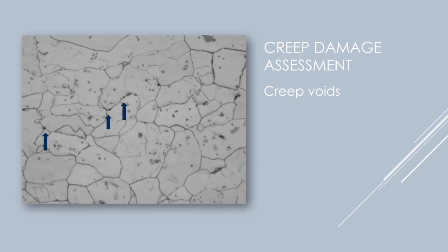So you can see all those little balls at the grain boundaries. Each one of them is a void. So they're not a particle, they're actually a little void. I've got three pointed out, and they're occurring on the grain boundaries that are at right angles to the principal stress, in this case the hoop stress. So the hoop stress is going vertically.